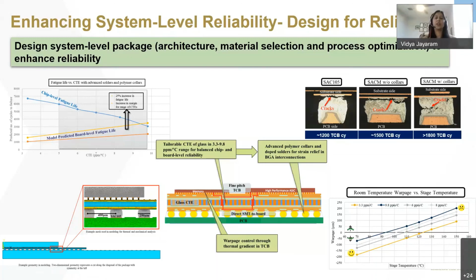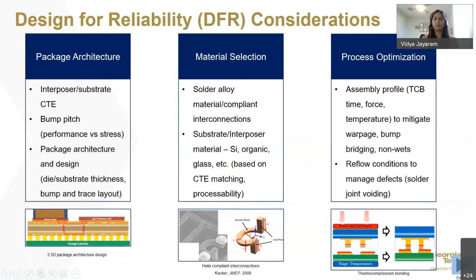So these were critical learnings in terms of modeling for the fatigue life, understanding what kind of materials we would want to use, and picking our process conditions to get the least warpage possible, so that we don't see any early failures or the latent failures caused due to process and yield. And at the same time, use these advanced materials or strain relief mechanisms to extend our reliability. So I think that was a good example in terms of how we went about dealing with failure, managing it, and extending our reliability accordingly.